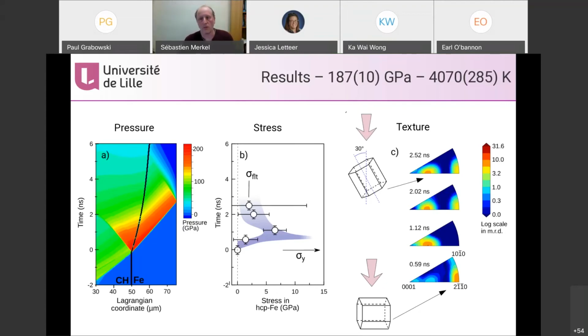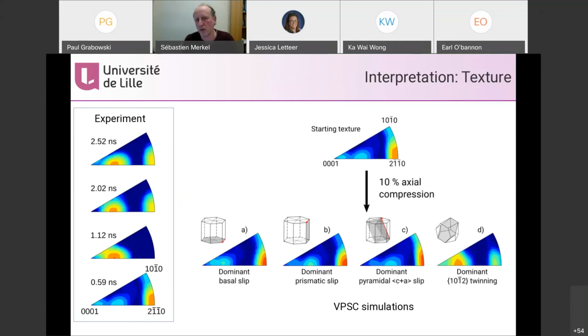So we can try to do modeling of texture evolution. It's something we do very commonly for HCP metals. This is the VPSC simulation, viscoplastic self-consistent, where I can force a deformation mechanism to take over the plasticity and grain orientations. And this is the result. This is the type of textures we measured in the experiment as a function of time, as the shock is moving through the material. And this is the simulation results. So here the starting texture in the simulation is the experimental texture after transformation.